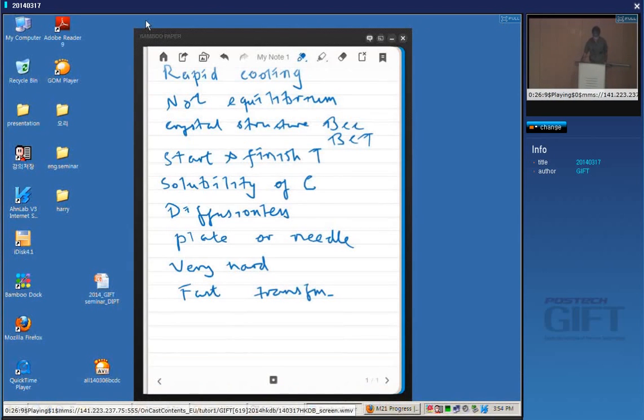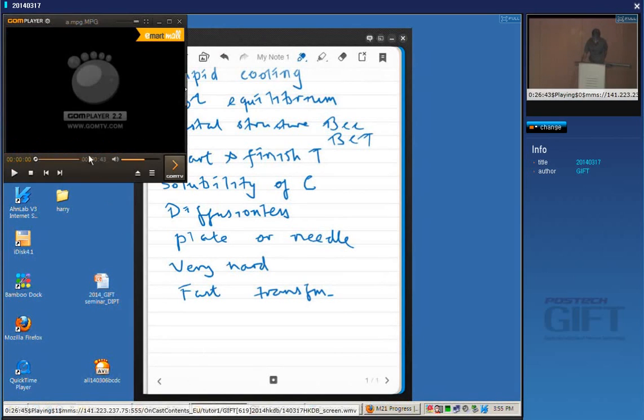So that virus emphasizes the change in shape when you get martensitic transformation. If you've got a change in the crystal structure, and crystal structure is just the way in which the atoms are arranged, if you change that pattern, there must be a change in shape if there's no diffusion, right? Just like if you take a square and you shear it, then you've got a different shape, and your shape change is a shear. And the virus exploits that to form a hypodermic needle.